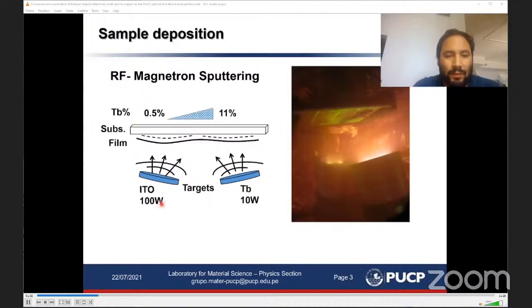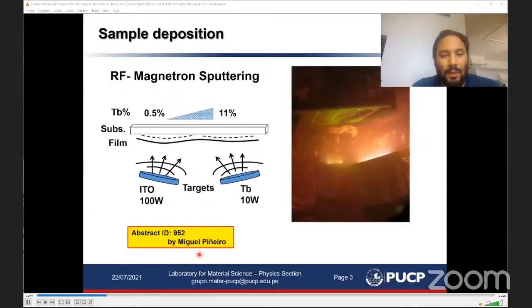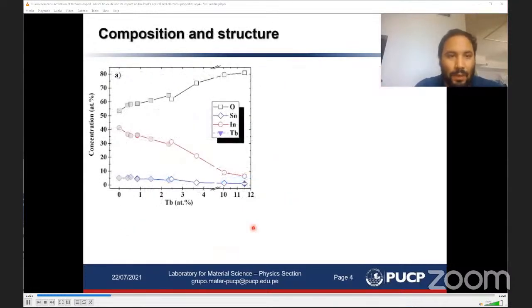Also, we study and characterize ITO films without any terbium grown in a similar fashion. If you're interested in details concerning these results, please visit the abstract ID and the work presented by Miguel Piñeiro. Here I'm showing you the elemental concentration versus the terbium concentration of the samples we have grown. And we will be focusing on samples in this concentration range of terbium, due to the fact that for higher concentrations we will have the concentration quenching effect of the luminescence.